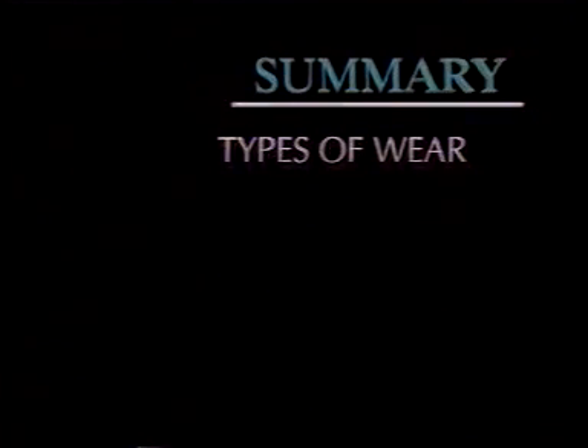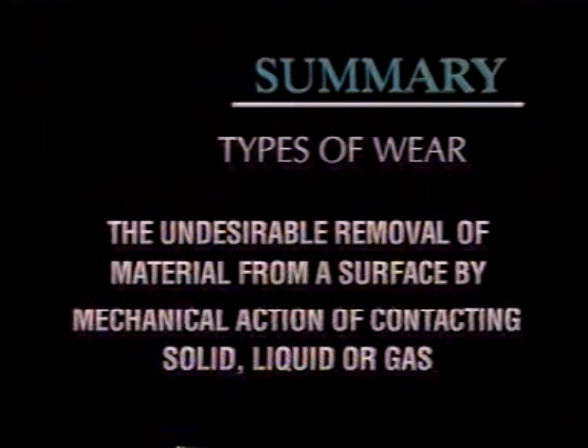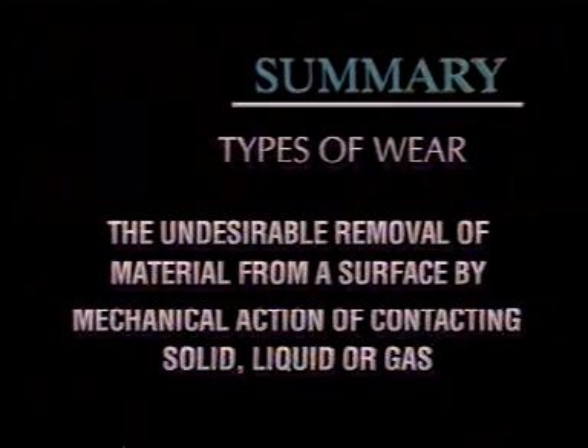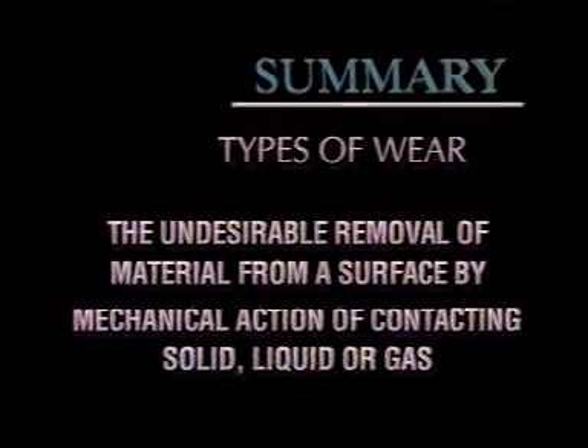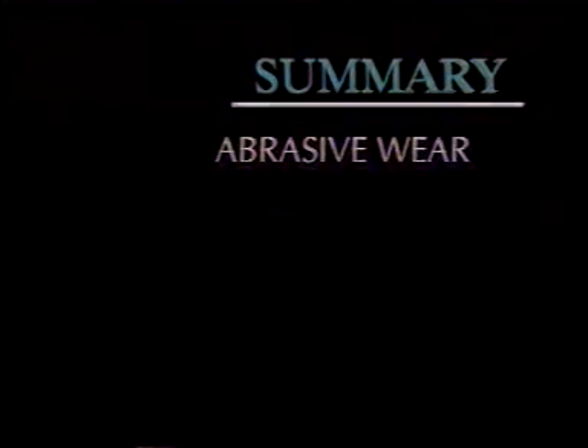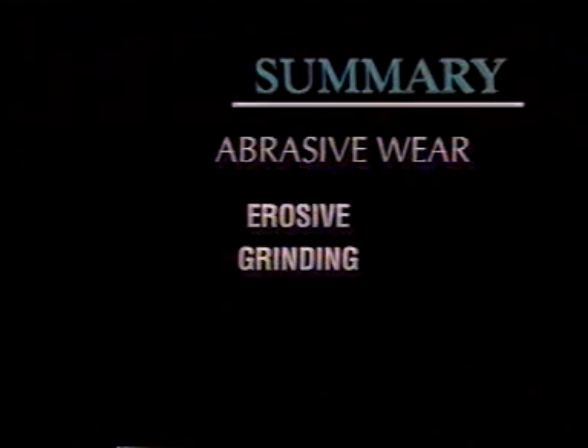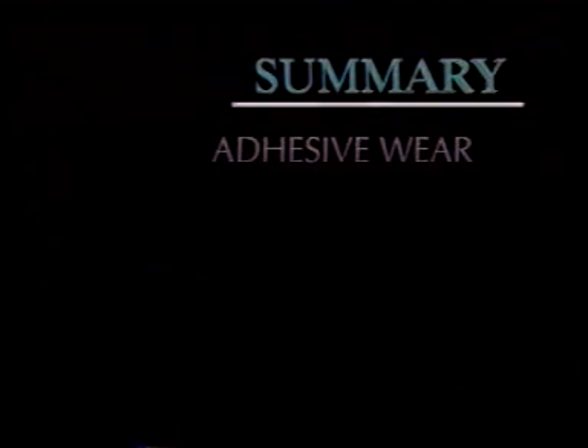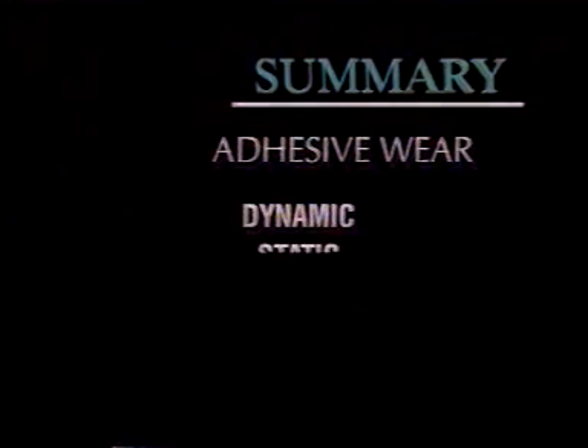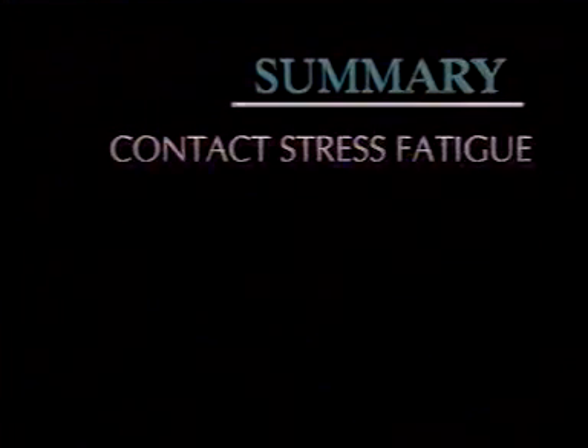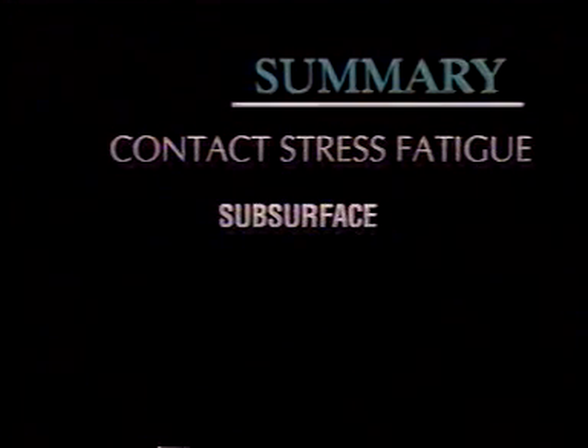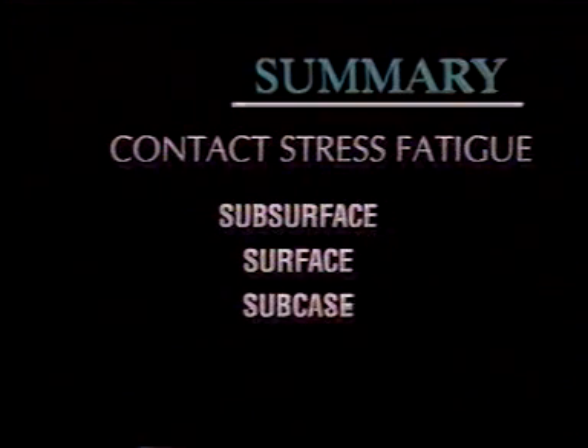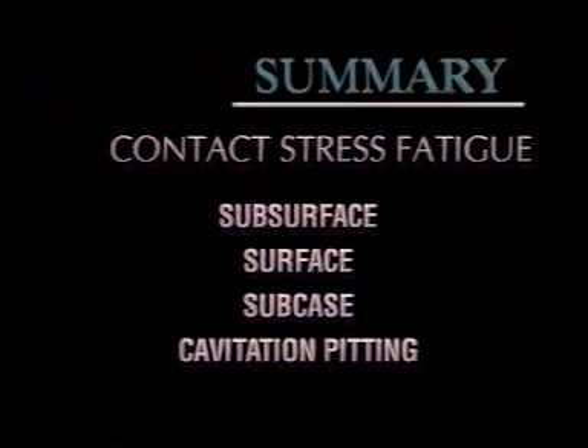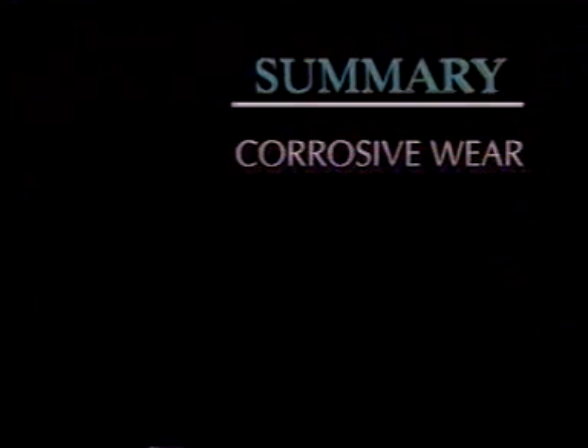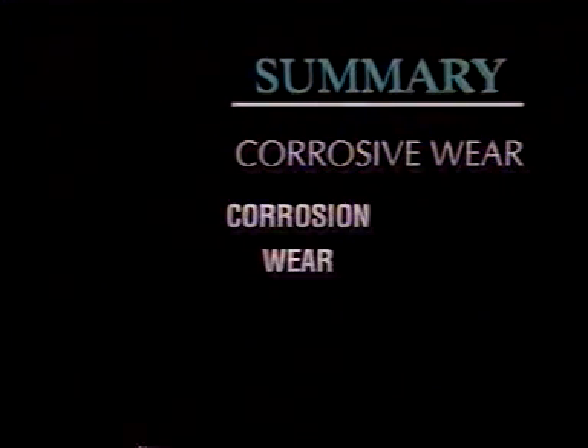Summary: types of wear. Wear is generally defined as the undesired removal or displacement of material from a surface, primarily by mechanical action of a contacting solid, liquid, or gas. Abrasive wear can be erosive, grinding, or gouging. Adhesive wear can be dynamic or static. Contact stress fatigue can be subsurface origin, surface origin, subcase origin, or cavitation pitting. Corrosive wear is the combination of corrosion and wear.